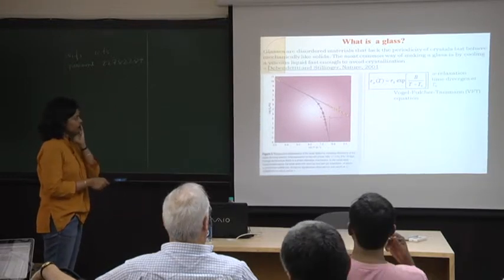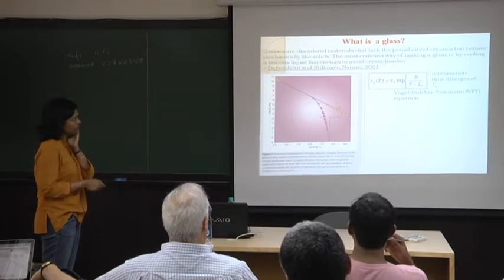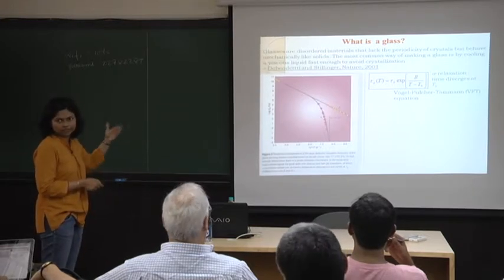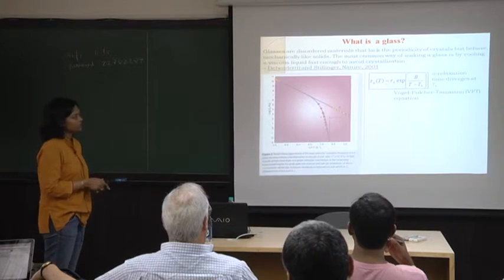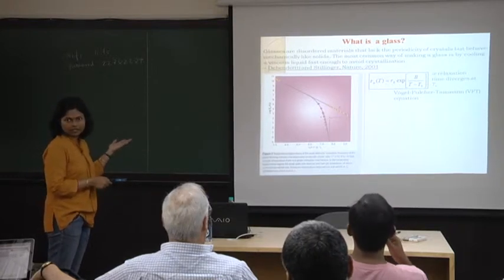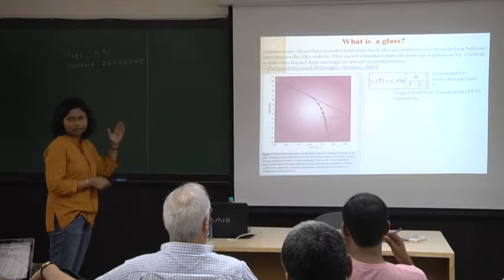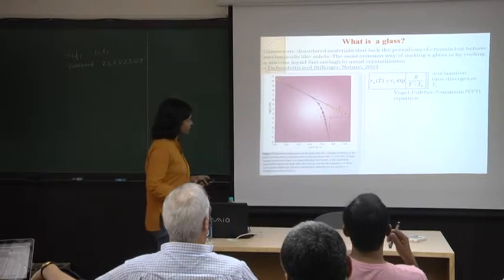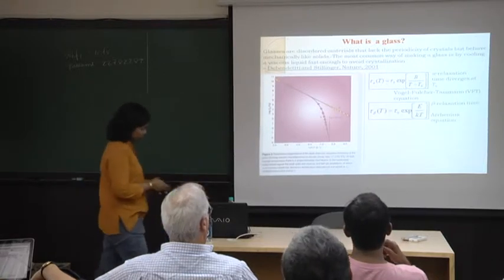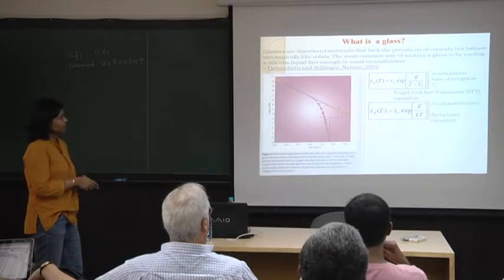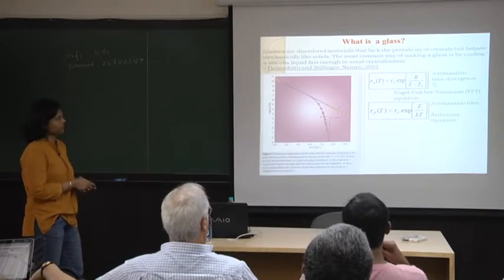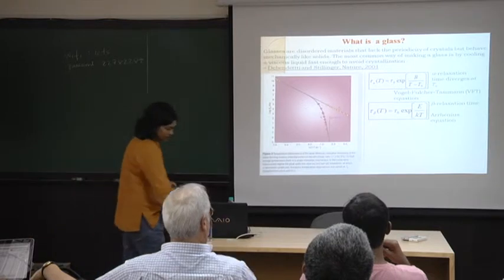You can fit it to something called a Vogel-Fulcher-Tammann equation. T0 is called the Vogel temperature. It will keep coming back. B is something called the fragility. It tells you how rapidly you are approaching your glass transition temperature. For this faster relaxation, okay, it's an Arrhenius process, and it goes like this.